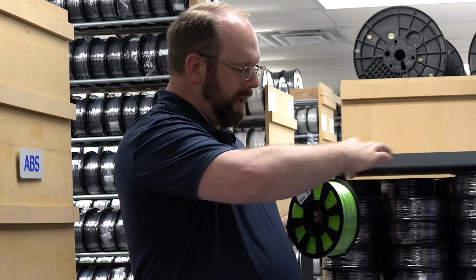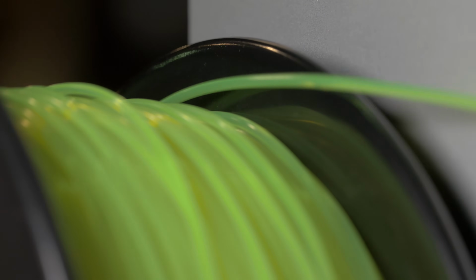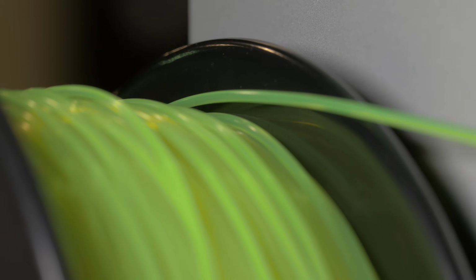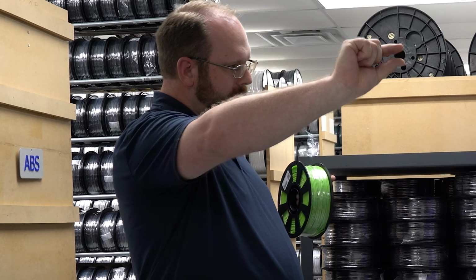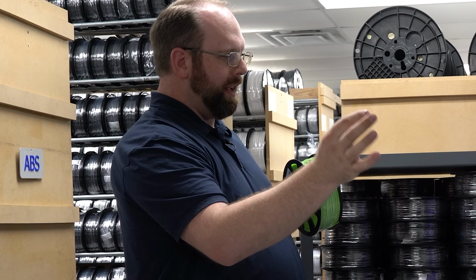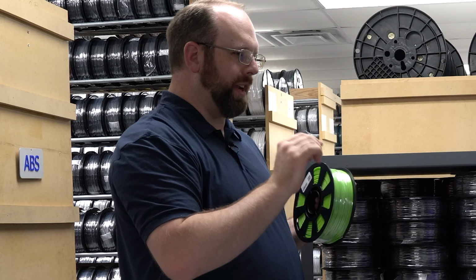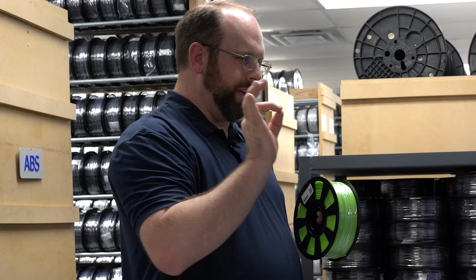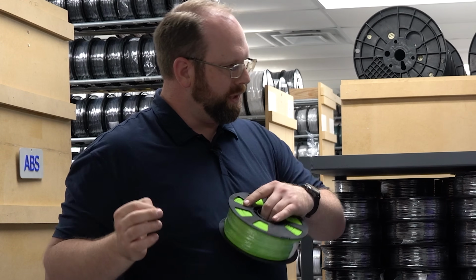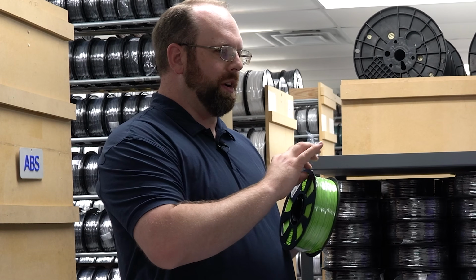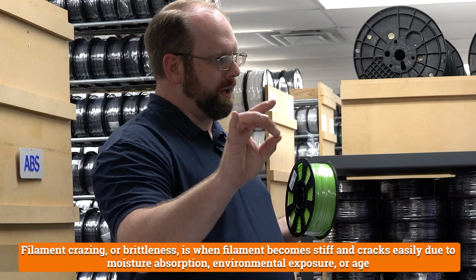And so when you take it and you put it in your tube and you straighten it out, well, now you've bent it. And depending on the filament, depending on a lot of variables, you get a bunch of micro cracks along the inside of that curve. Okay. And then when you leave that set inside your tube, those cracks can grow. And especially when you disturb it, when you pull it out, it can finish breaking the filament. Yeah. So we call that crazing. It actually is filament crazing.